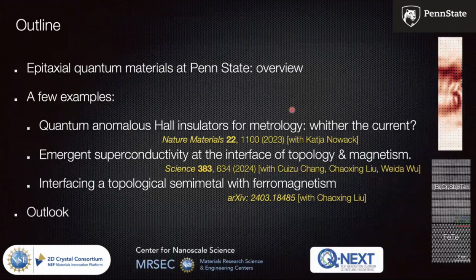But we have some model theory to try to explain the data and so on. I think it's quite interesting. It's interesting that you take a material that's an antiferromagnet, you take a material that's a ferromagnetic quantum anomalous Hall insulator, put them together, and you get superconductivity. And the superconductivity is such that it proximatizes the entire ferromagnetic topological insulator right up to the surface. And this is over lengths of something like 10 nanometers or so.